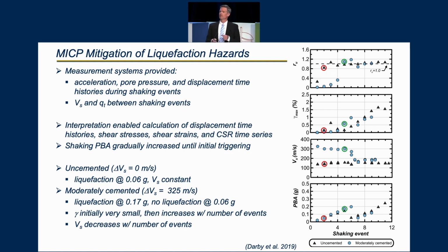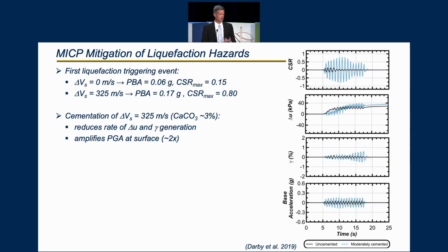So we'll just grab those two events, the 0.06 event and the 0.17 event, and compare them in the same figure, and you can see that right here. The maximum CSR felt in the upper portion of that soil was 0.15 for the uncemented case, but it was up to about 0.8 for the cemented case. And looking at the data in a little bit more detail, you can see that the cementation reduces the rate of excess pore pressure generation as well as the rate of strain generation. And it also, on the other hand, does amplify the accelerations at the ground surface a bit. So that's something we'd have to consider if we provide this kind of improvement.